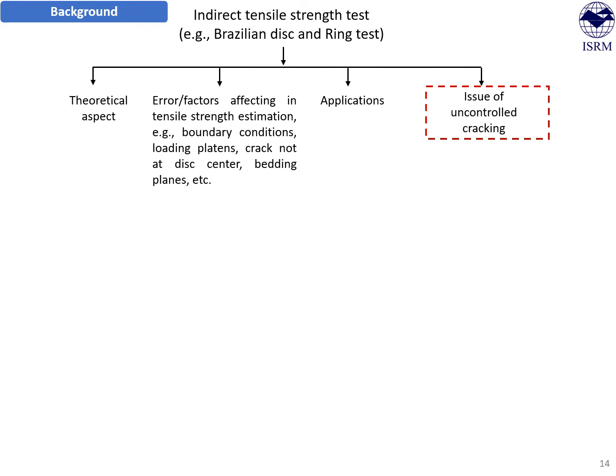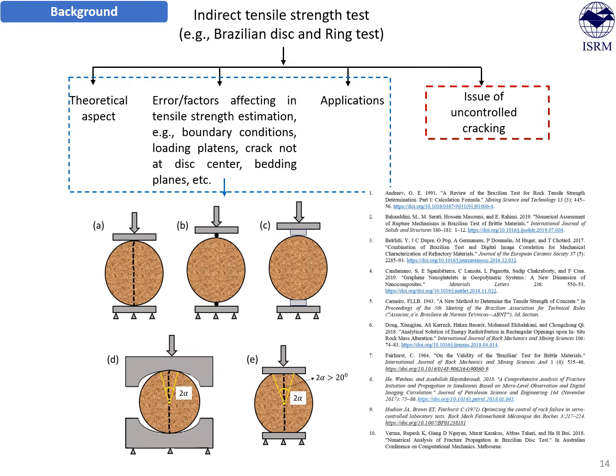Thereafter, we again went back to literature to evaluate whether there has been done anything regarding this issue of uncontrolled cracking. And we realized lots of work has been done. However, most of this work in literature around indirect tensile strength test was focused on ensuring the crack initiation at the center of the disk. A number of changes were recommended in literature to change the loading angle to ensure that the crack initiates at the center of the disk specimen.